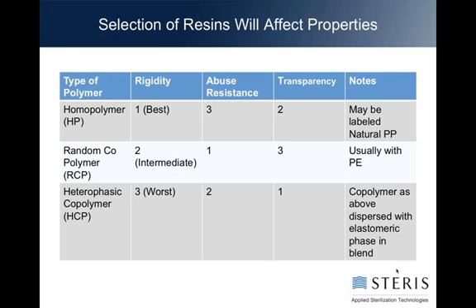Okay. One of the ways you classify a polypropylene, when you get a resin for manufacture, you always get a specification sheet on it. Its description at the very top, the first thing it will usually say, is either natural polypropylene or homopolymer of polypropylene. It'll say a random copolymer. Sometimes it'll use a variation on a random copolymer called a heterophasic copolymer, which is just another form of one. But the reason that is important is that it tells you right away whether or not you should be highly concerned about the stability and radiation.